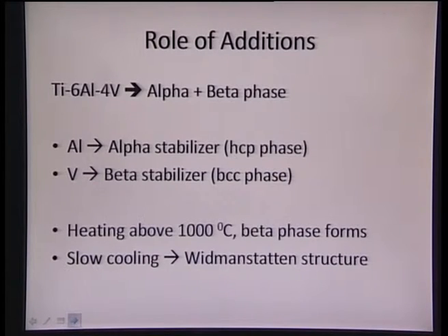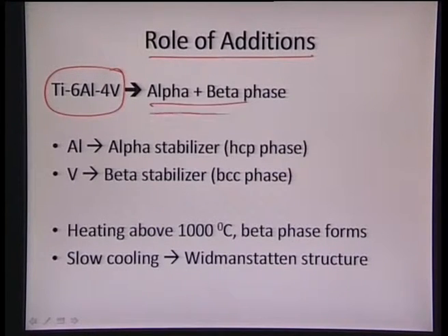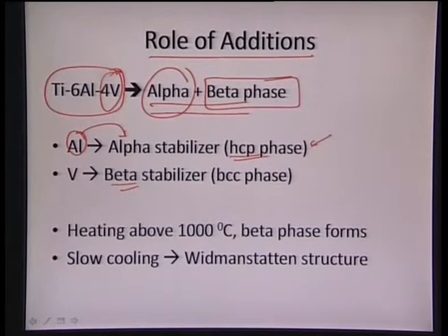Again, as I said earlier, the role of additions, they go on to titanium 6 aluminum 4 vanadium. It forms a dual phase microstructure. So alpha comes basically from the titanium part. At the same time, alpha is also being stabilized by aluminum. So aluminum also acts as an alpha stabilizer. It renders the HCP phase much more stable. But the presence of vanadium helps in forming a beta phase. So we see this titanium 6 aluminum 4 vanadium, it is a combination of alpha plus beta phase.